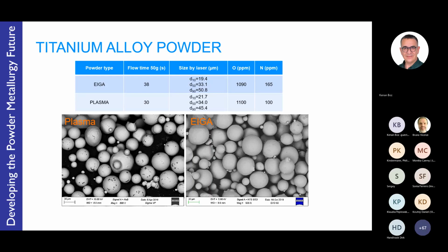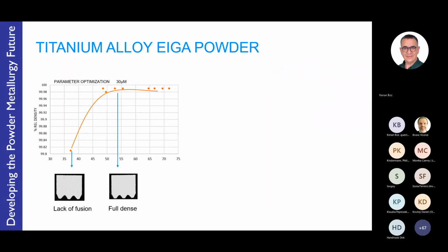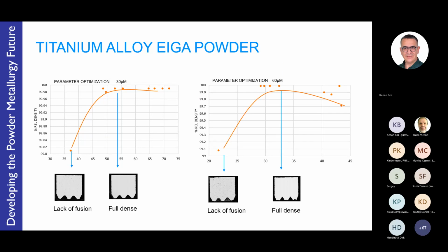Comparing plasma atomized and electrode induction gas atomized, very little difference in terms of morphology and flow characteristics, and the size distributions are very similar, as well as the oxygen and nitrogen contents, which are crucial in terms of mechanical performance. Titanium alloys. Here we see different layer thicknesses from 60 microns and 30 microns, optimized for the electron beam process. And moving from 30 microns to 60 microns effectively doubles the speed of the processing.